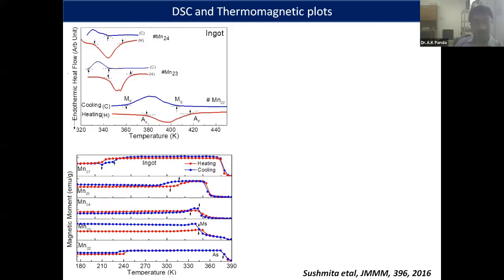And this is where we use the thermomagnetic plots in combination with differential scanning calorimetry to find out where the magnetic transition is happening, at the same time where the austenitic transformation is taking place. So this idea is very important when you try to find out the entropy of the material.